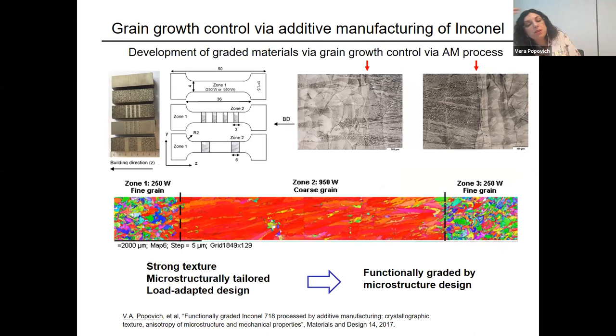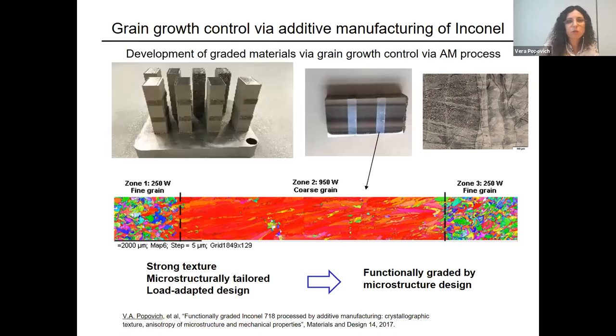And what can be done with additive technologies is you can blend these kinds of microstructures together. And in the next slide, maybe some of you can already guess why you would like to have both: in some locations fine grain structure, yeah, in some locations really this 001 orientation. So this all red, what is shown here, is one big grain, yeah, elongated at its specific location. And this is how the interface between the two can look. So this is just an example of how we can grow this, tailored in different locations. In the middle, you can see these grains along this orientation. All around is the fine grain matrix here. Yeah?